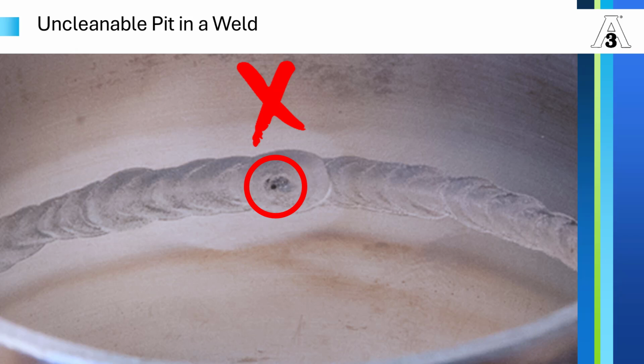Even the environment you're welding in. This is an interesting thing, but if you go to a fabricator's shop, almost all fabricators now have 100% stainless steel shop environments. One of the reasons is that airborne dust can make its way in. So if you've got a heavily burdened, dirty environment, the impurities in the air can make their way into that weld pool as you're welding, and it can cause that as well.